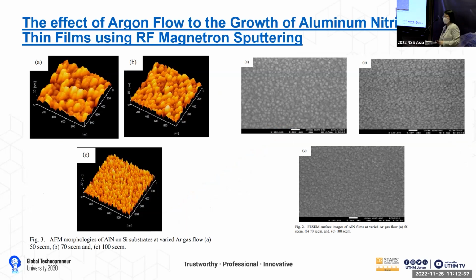He was actually doing sputtering of a monolayer of aluminum nitride thin film on the silicon wafer. So he looked at the argon flow rate effect on the sputtering of the aluminum nitride. So you can see that as the flow rate increases, the grain size of the sputtered aluminum nitride gets smaller. So the AFM actually gives you the roughness information. It doesn't show in the other image, but the AFM gives you the details of the roughness and also the grain size.